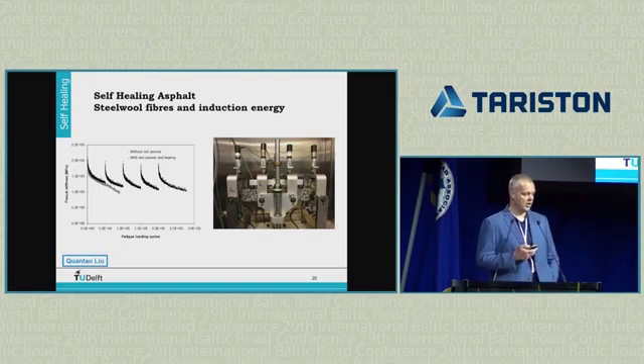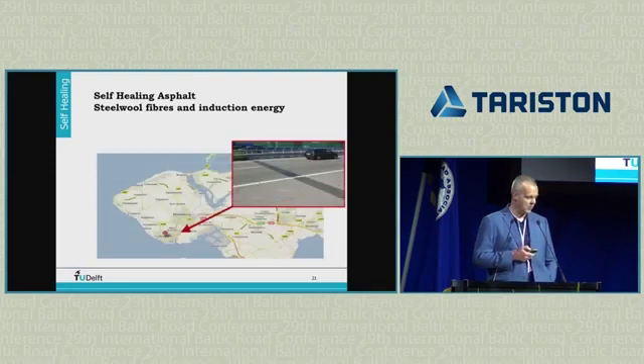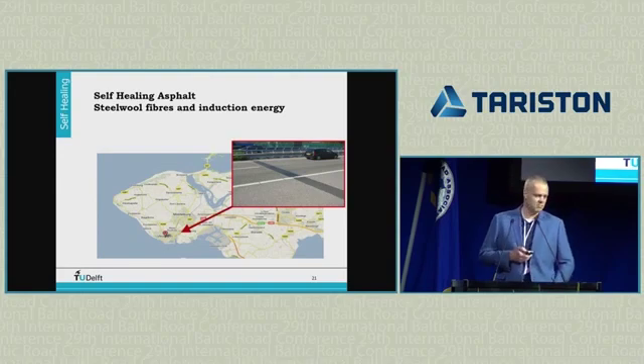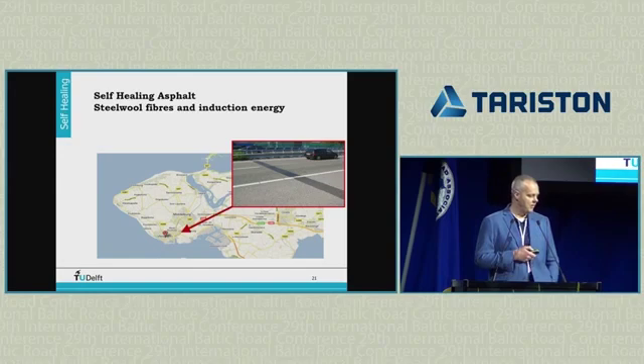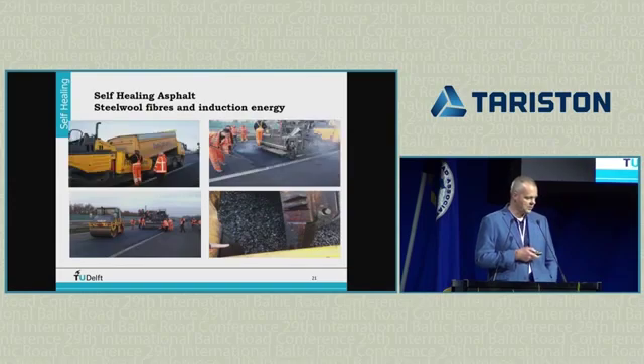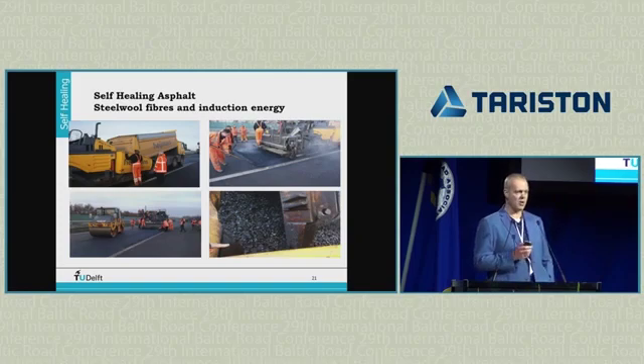So we did this on normal samples, on aged samples, and see what kind of differences we got and how it improved. Also, the government, Rijkswaterstaat in the Netherlands, they saw what we are doing, and they said, well, we have to try this out. So they gave us in 2010 already a test section, a part of a highway in the south of the Netherlands, where we could place 400 meters of asphalt and then test it over the years, heal it over the years, and also monitor it. So this was when we were placing the material in 2010. So it's normal asphalt pavement machines you need, normal mixing plant. Just add these steel wool fibers, small fragments to it, and mix it through.